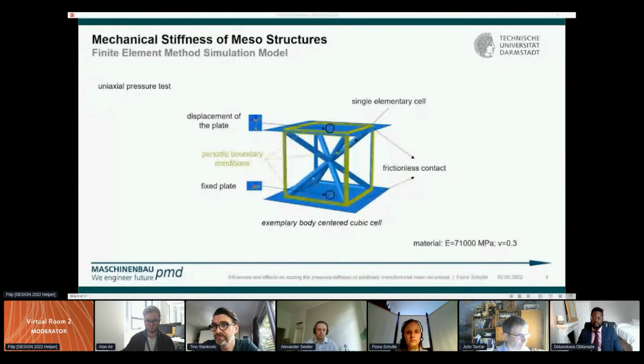The mesostructure's stiffness properties are identified using a finite element method simulation model. As an exemplary load case, uniaxial pressure is examined here. To simulate the pressure stiffness of a mesostructure, a single elementary cell is modeled between 2 rigid plates with frictionless contact conditions. The lower plate is fixed, while the upper plate is impinged with a displacement in vertical direction, and the response force in the reference point is output.